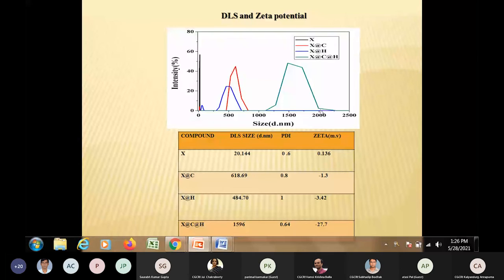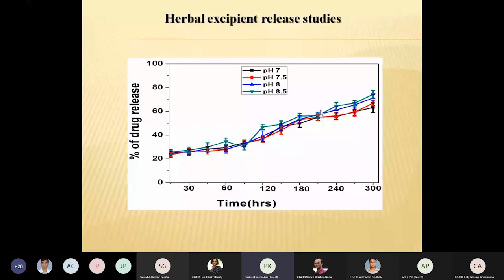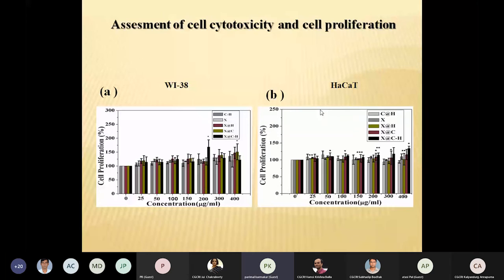And their release study has been done at different pH. So in a wide range of pH, their release is almost the same, and their effect is not really toxicity, rather proliferation. As you can see, we optimized a dose of this for fibroblast WI38 or HaCaT, which are keratinocytes. So we optimized the dose which can help them to grow, and then we did the